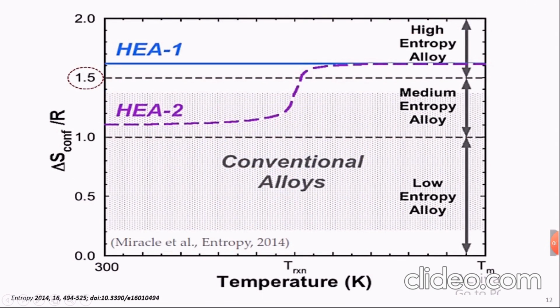configurational entropy is related to the gas constant. So if delta S over R is over 1.5, it will be high entropy. If between 1 and 1.5, we have medium entropy. If lower than that, we have low entropy alloys or even conventional alloys.